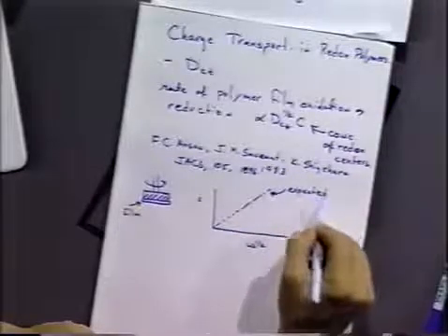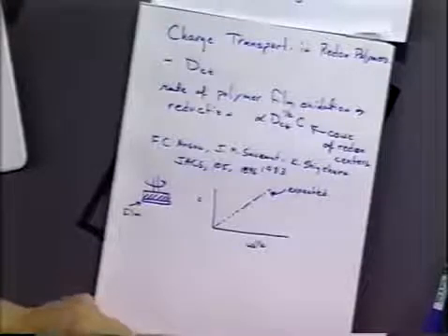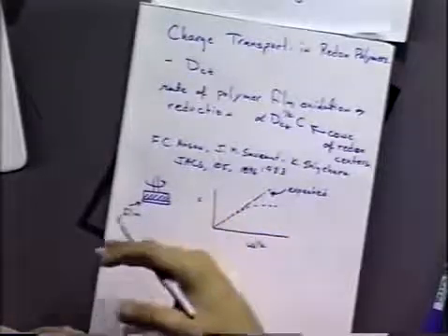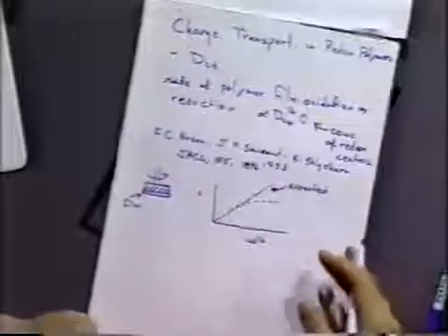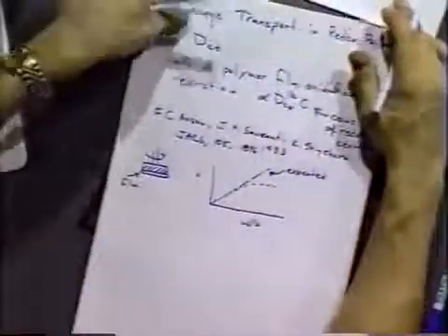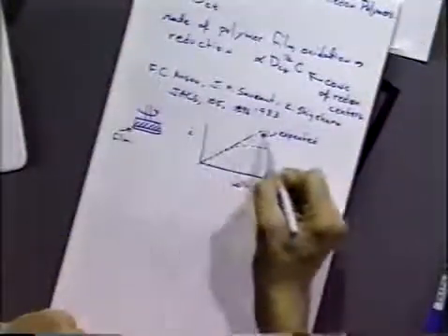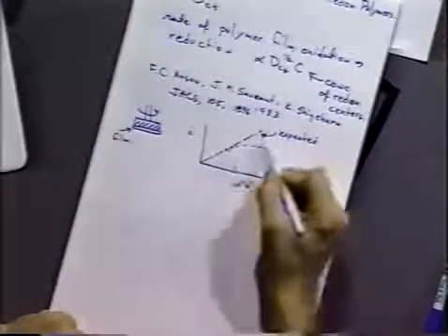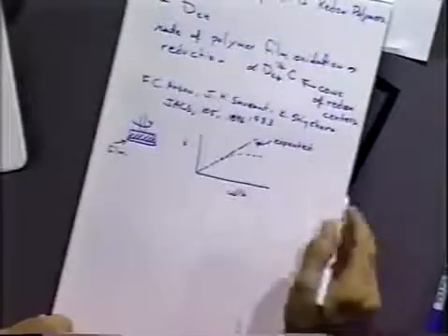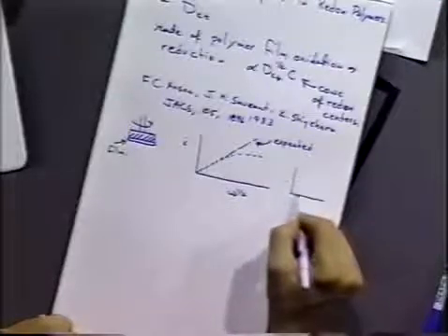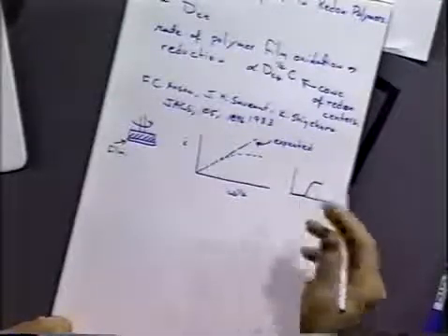In practice, what they saw once they put the redox film on the system is behavior like this, which suggests that there is a mass transport limitation. In fact, the mass transport is not mass but charge in this particular case, because we've made sure the mass transport would be the case for a bare metal electrode on the surface. So in that regard, we're now having a limiting current that's limited not by the rate of mass transport, but by the rate of charge transport through the film.